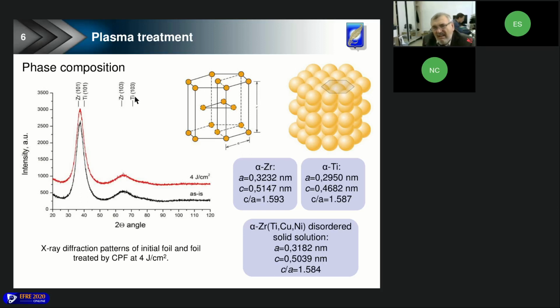It is known that zirconium and titanium form a solid solution in the whole concentration range, both for low-temperature and high-temperature polymorphic modifications, I mean in equilibrium conditions. So one can conclude that a zirconium-titanium disordered solid solution based on the low-temperature phase having the hexagonal lattice, maybe containing copper and nickel atoms as alloying elements, was the main phase of the foil produced by quenching from the melt. Lattice parameters calculated from the diffraction pattern are shown on the slide. You can see that the values of lattice parameters were between the corresponding values of zirconium and titanium, but the C/A ratio for the disordered solid solution was less than the corresponding values for zirconium and titanium. That can possibly be attributed to the influence of alloying elements.